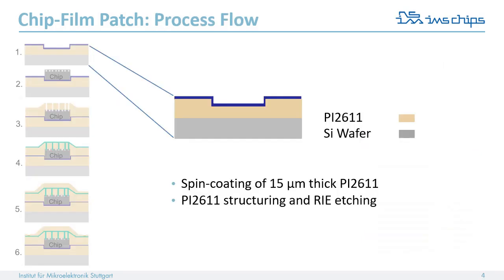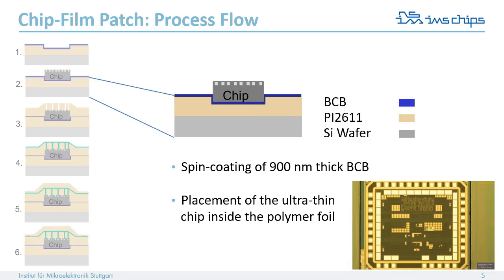The wafer-based ChipFilm patch process is performed under CMOS-compatible cleanroom conditions, and the process starts with the preparation of a 150 mm silicon wafer by gradually spin coating polyimide on the wafer. The polymerization is finalized at 350 degrees to obtain the required material properties. The polyimide is then structured photolithographically and etched with a reactive ion etching process to form a few micrometer deep cavity. A thin layer of benzocyclobutene is spin coated on the polyimide, which serves as the adhesive and facilitates the chip adhesion to the polyimide.